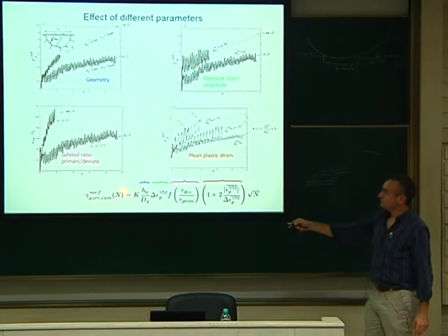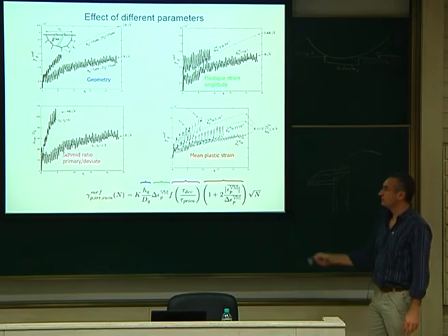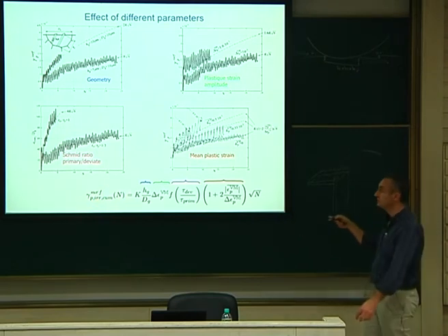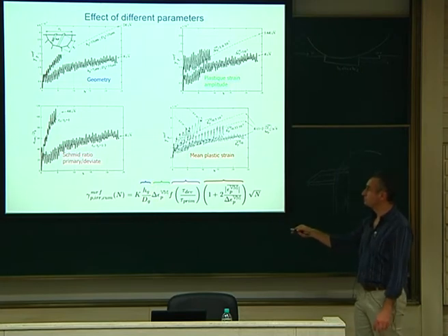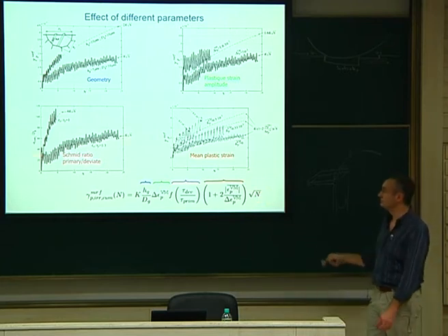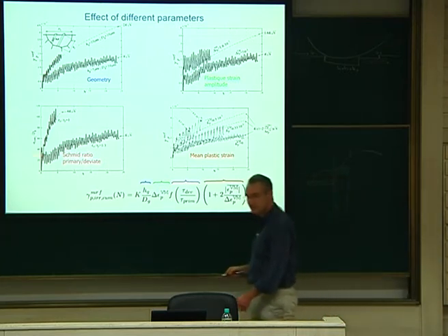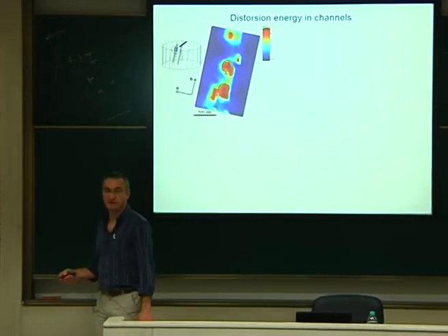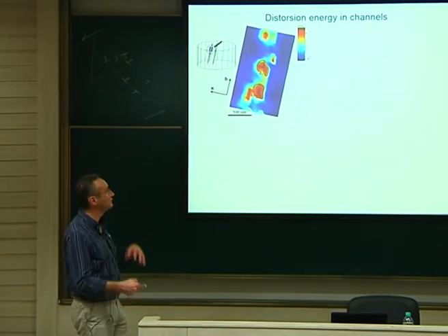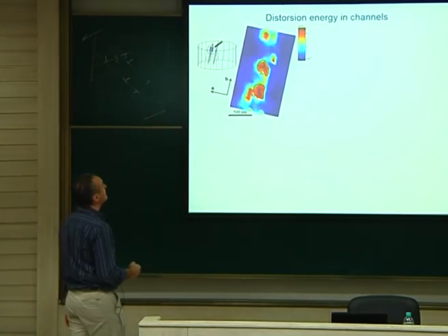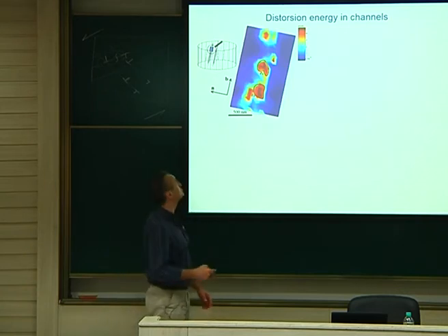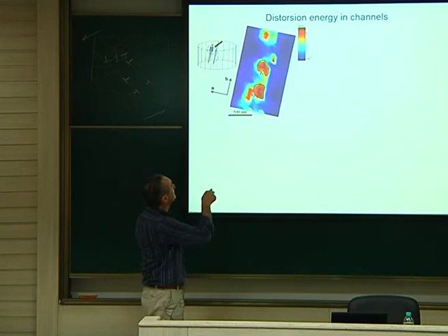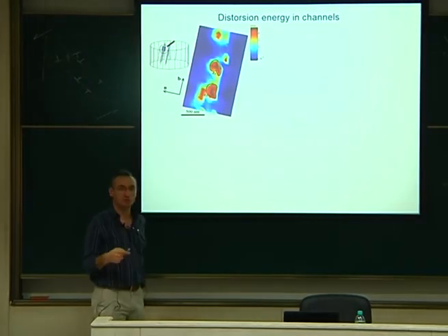So finally, the shear stress at the surface is evolving with many parameters that we investigated, like the aspect ratio, plastic strain amplitude, mean amplitude, and then the loading, like this such relationship, okay? Again, the square root of n is there, okay? Now I want to know if this will create a crack. This was my question. Is it possible that a crack appears during that loading? So here to do that, I want to compute stresses and energy in the band typically. So this is my band here. I zoom on it, and this is the energy I compute. So energy is computed like sigma epsilon.